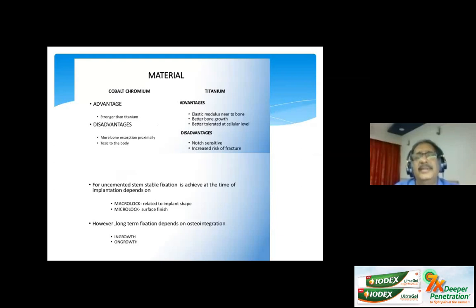The types of material we use are either a cobalt chromium or a titanium stem. Titanium is now getting more preferred, but its disadvantage is that it is notch sensitive and there is a slightly increased risk of fracture. The cobalt chrome disadvantages are more stress shielding and resorption of proximal bone.